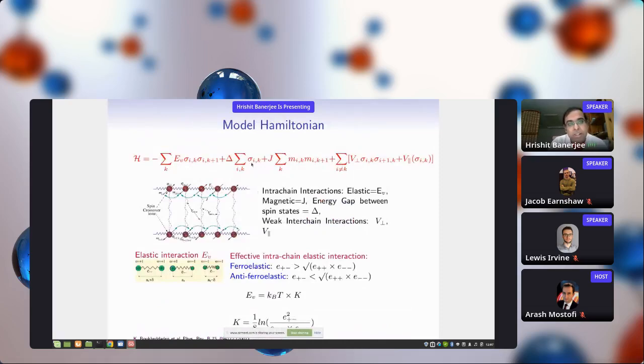So with that, we construct a model Hamiltonian which has somewhat been studied in literature, and this model Hamiltonian consists of various terms. The first term is basically the intrachain elastic interaction which couples the pseudo spins. Then you have a difference in energy between the high spin and the low spin states. Then you have the magnetic exchange which couples the real spin quantum numbers, and finally you have some steric and elastic effects, steric and also electrostatic effects between the chains, which are very weak, mind you. And hence, mostly the strong interactions are the elastic intrachain interaction and the magnetic intrachain interactions.